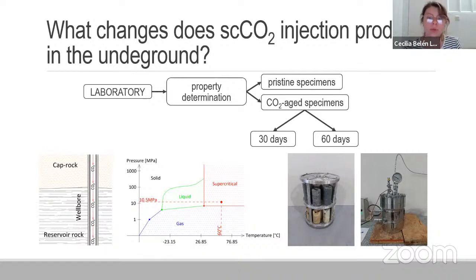The aging process basically consisted of introducing these pristine specimens inside a carbonation cell or carbonation chamber, as observed in the slide. In this carbonation cell, the pristine specimens were introduced in a water-saturated state. The objective of this was to allow quicker diffusion of the CO2 inside the porous structure of the rock.